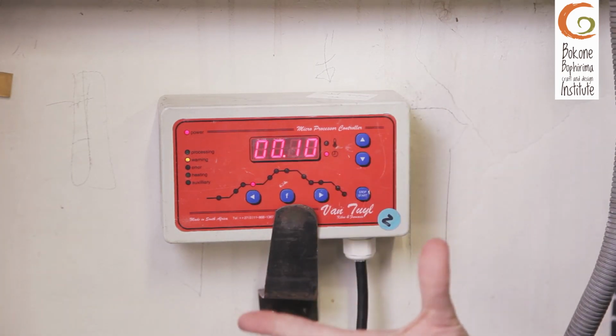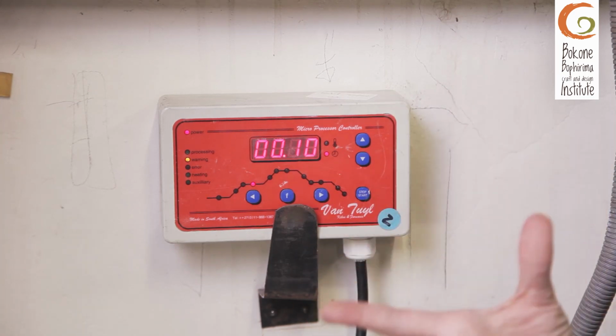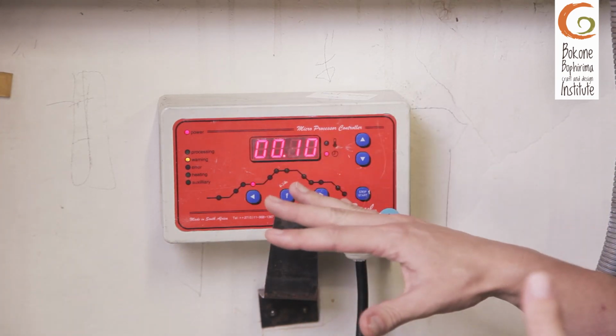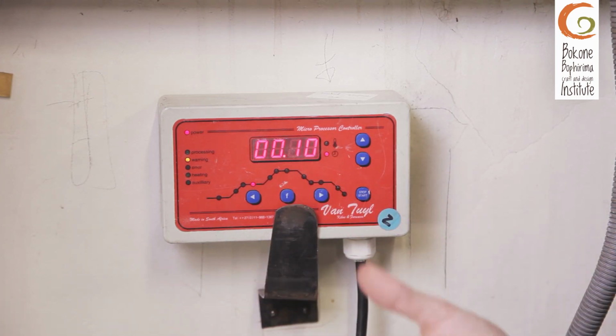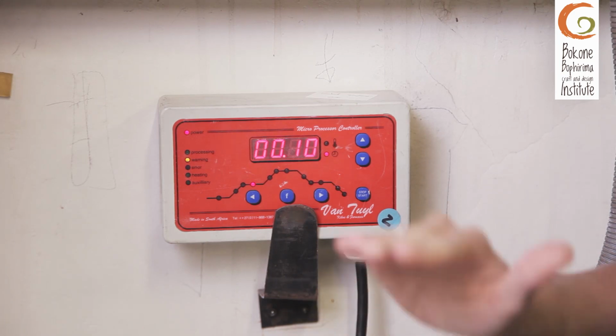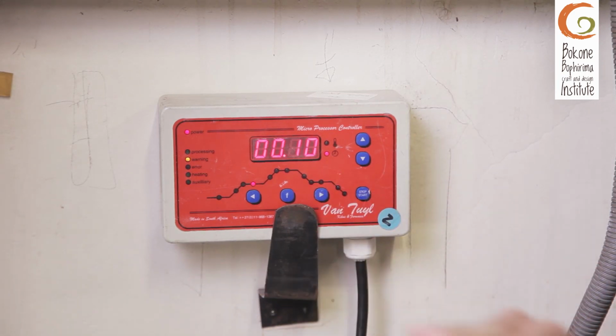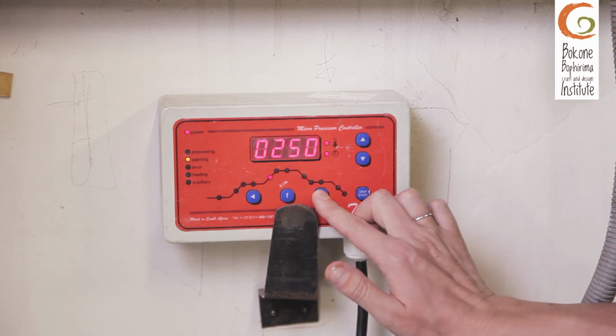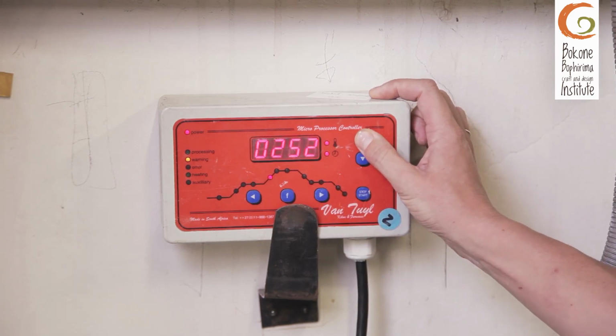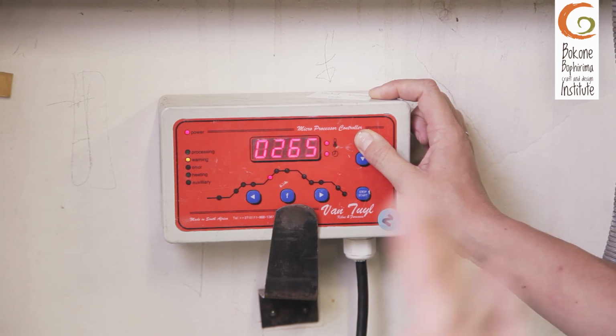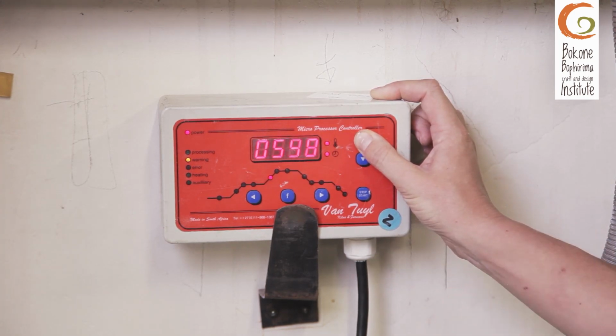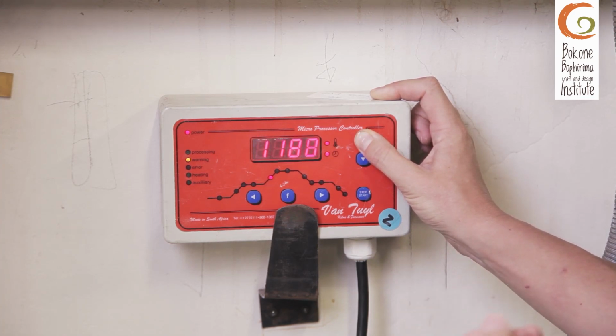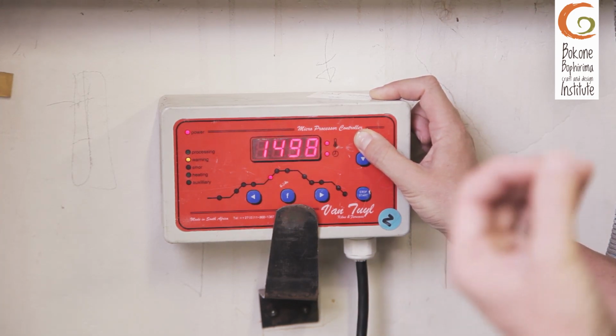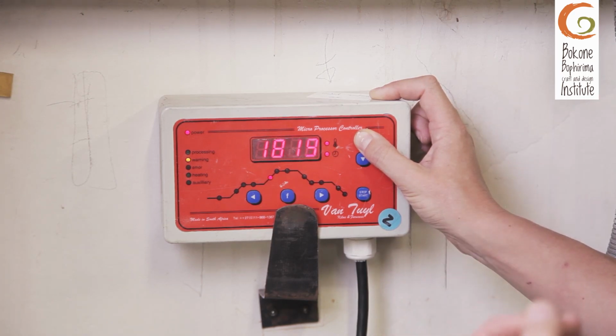Our glass is not that thick, so we don't need to allow it to soak for that long. So why we put a soak in is to make sure that our glass, not just the top surface, but the entire glass, from the bottom to the top, has evenly heated up in between. Then we're going to actually go up full. Our glass has no tension in it. Because our glass has no tension in it, we don't have to worry about taking it up slowly from 580. Remember, above 580, we can work at a much faster ramp if there's no tension.